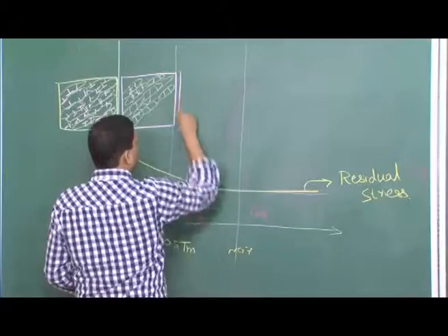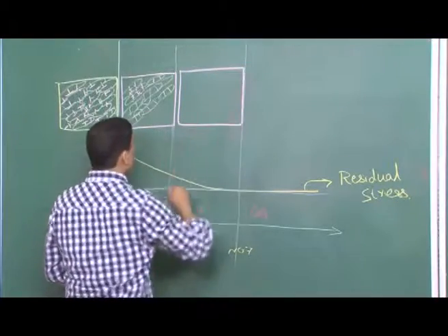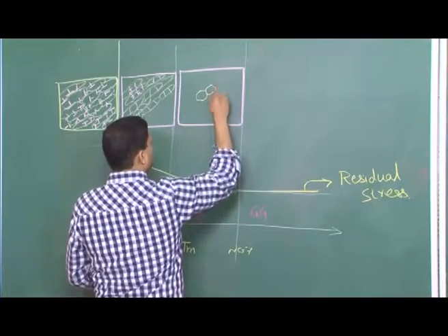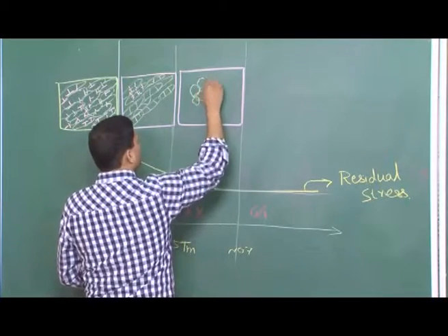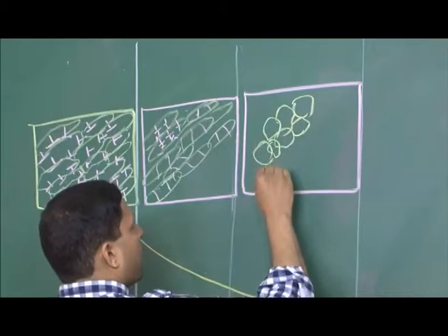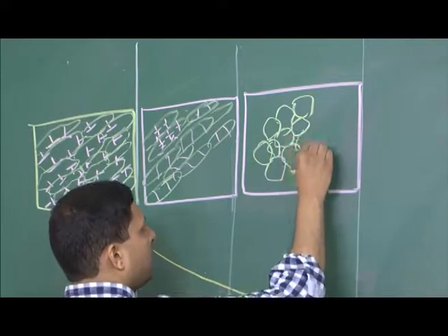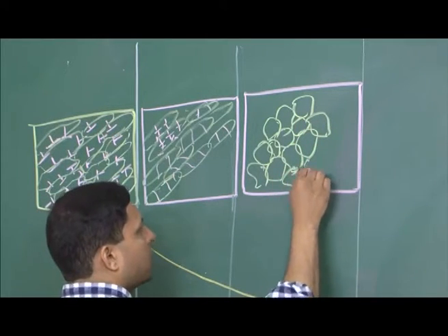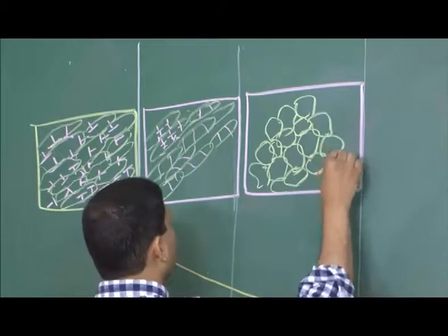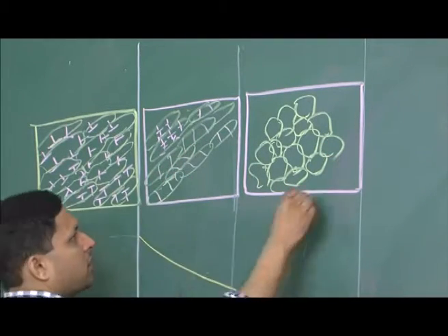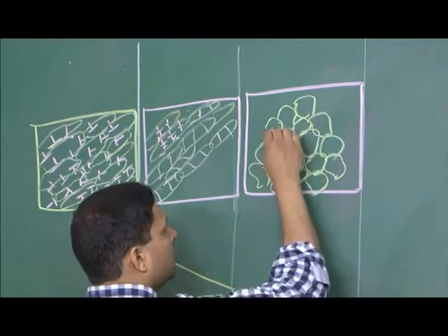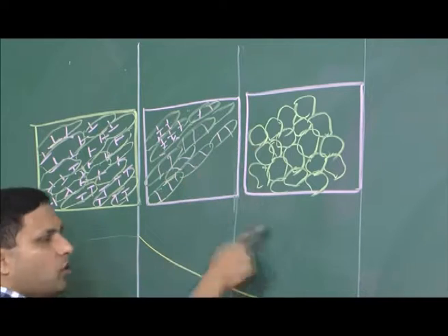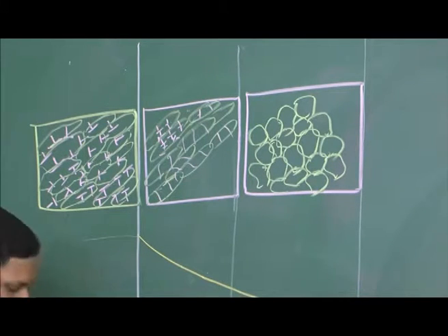In the recrystallization zone, you start to see some new grains, small new grains all over, and therefore, you can see that these are what are called equiaxed, meaning in any particular direction it does not have longer growth. Here you could see that the grains are longer in this direction, but when you have recrystallization, these are all new grains and they are strain free. You can see they are strain free because there is no more dislocation structure inside the grains.